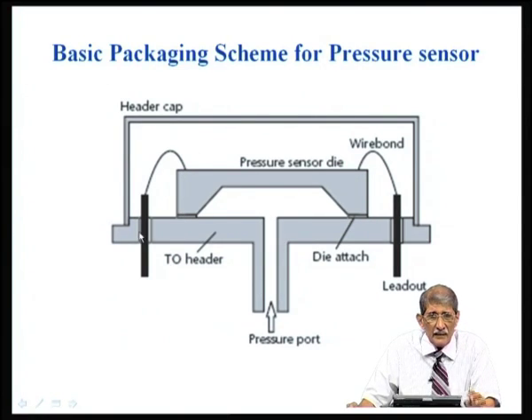This is actually a thick metal plate which is gold plated. Onto that you can mount this either by a technique known as eutectic bonding, that is, just keep the silicon in contact with this gold plated plate and just heat the temperature to about 400 degrees centigrade.